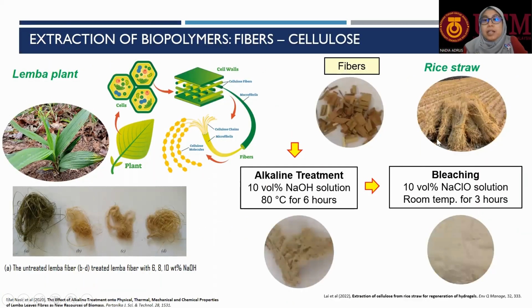Our group has also done some studies on other resources. So here is the rice straw, and the rice straw has been cut into small fibers, subjected to alkaline treatment for a certain time and temperature, and also bleaching. So here you see that the fibers are disintegrated into this lump, and this lump is bleached to remove the residual lignin.